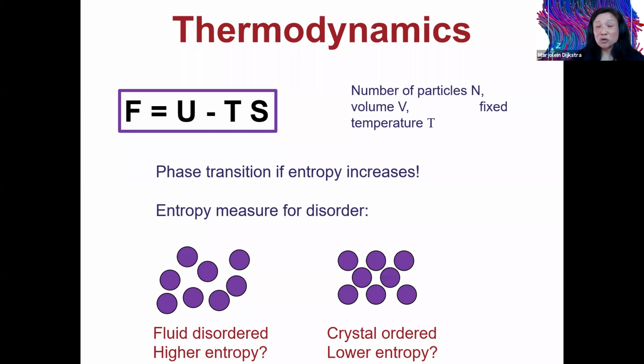For that, we have to go back to thermodynamics. And a phase transition only occurs if this results in a lower Helmholtz free energy. And the Helmholtz free energy is just the potential energy, U, minus T, the temperature, times S, the entropy, for a fixed number of particles N, volume V, and temperature T. And because only non-overlapping configurations contribute to the configurational integral or the partition function, the potential energy is always 0 for these hard particle systems. And so a phase transition can only occur if this results in an increase in the entropy.